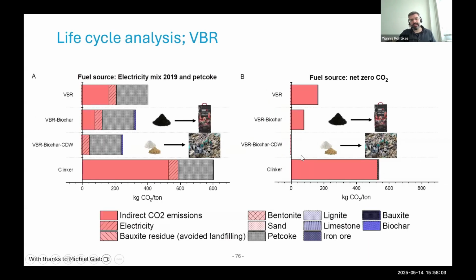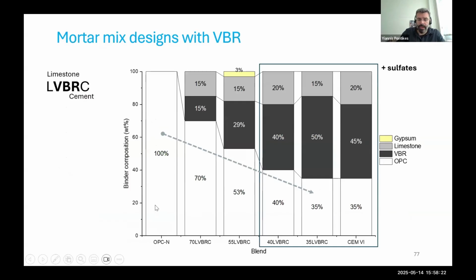And then you check the LCA and you see that, yes, depending on what you add and what your source of carbon is, you can have different environmental impacts. But in all the cases, you're doing better than the clinker today. So you can even go to very, very low amounts of CO2 per ton of VBR.